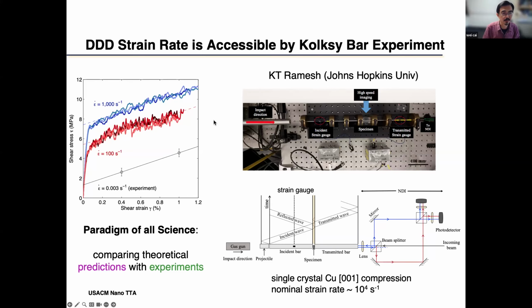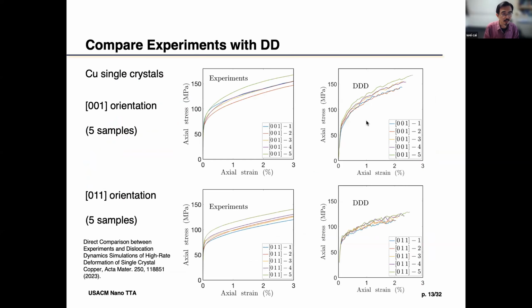Basically, it's an impact experiment. You have a rod that impacts it, and then the sample is here, and it's a single crystal copper at some specified orientation in compression. Also, the experiment was carried out several times, because every time you do it, the strain rate is not exactly the same, depending on the pulse of the detonation. But the strain rate is recorded, so we input the recorded strain rate into the DD simulation. So those are the simulations at exactly the experimental strain rate profile. Usually what happens is that if the strain rate happens to be a little higher, then your stress goes a little higher too. Okay, so we did 5 samples of 001 orientation compression, and then 5 samples of 011 orientation.